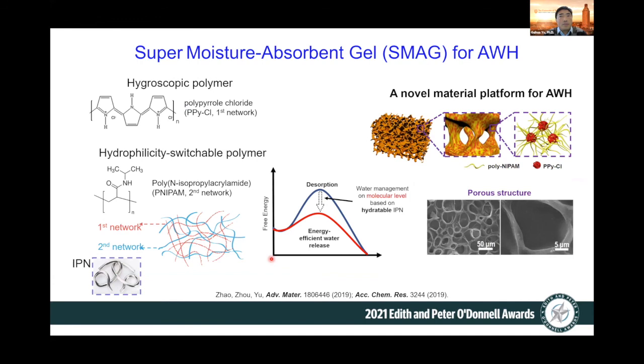So we recently developed what we call a super moisture absorbent gel, SMAG, for atmosphere water harvesting. This is a hybrid of two components. One is a hygroscopic polymer, chlorinated polypyrrole. The other is a thermal responsive, hydrophilicity-switchable polymer, polyNIPAM. This interpenetrating network can give you both high absorption of water, and due to this liquid-to-liquid transition, you can effectively reduce the barrier for desorption. So you have much more efficient water release. This is our design. We use polyNIPAM as the thermal responsive polymer network, and chlorinated polypyrrole as the hygroscopic salt to absorb the water vapor. They are highly porous, as you can see from the SEM image.